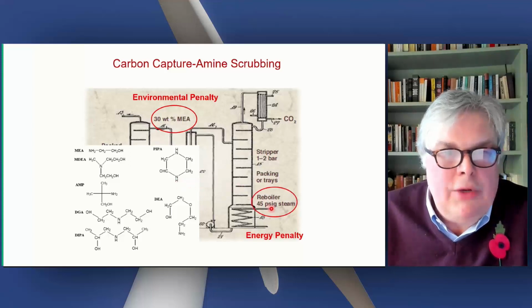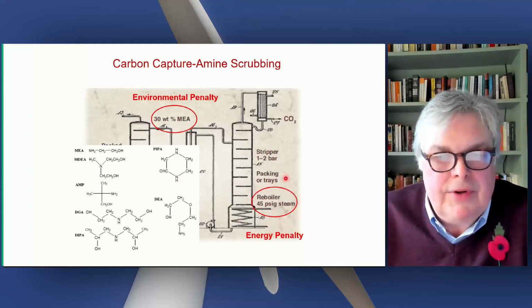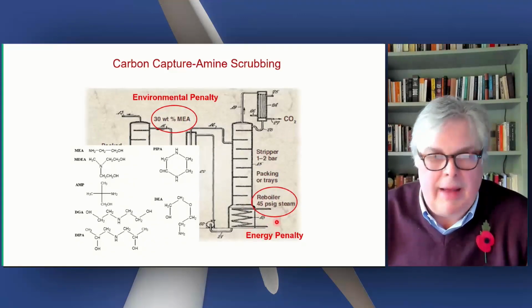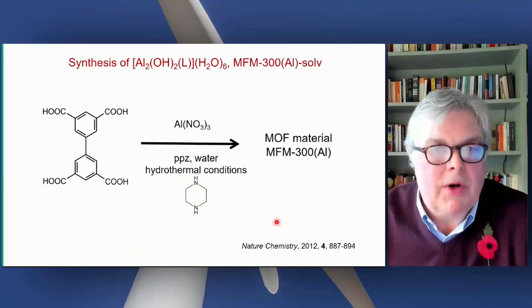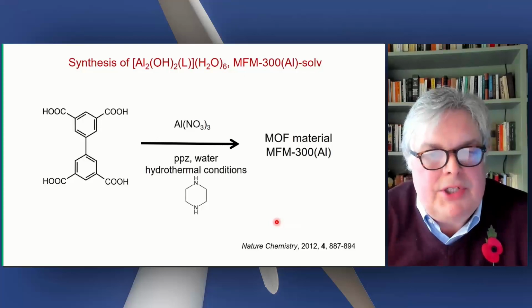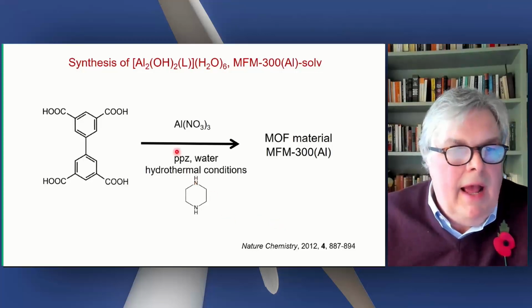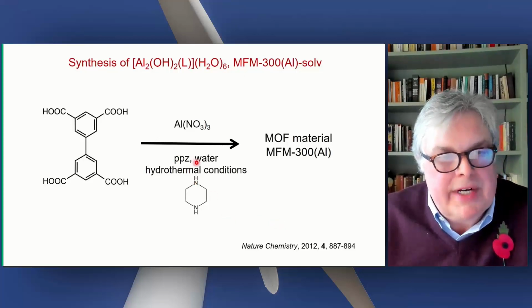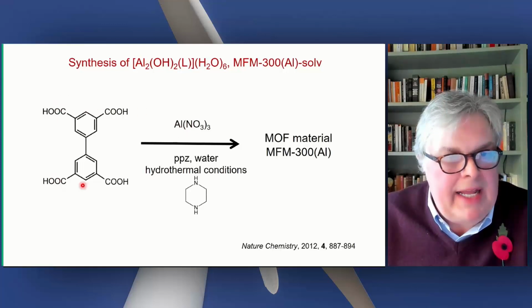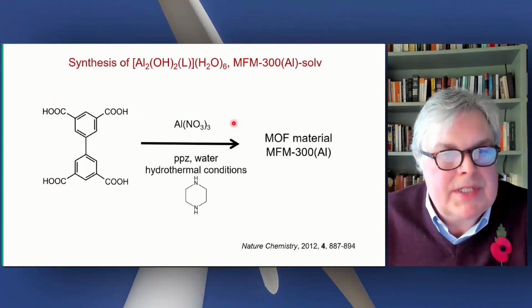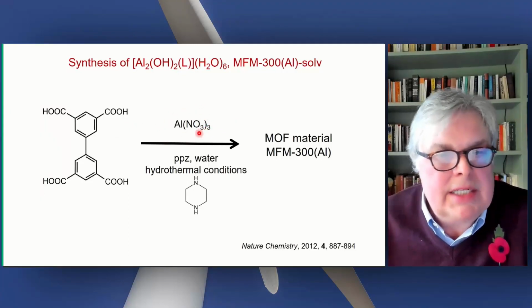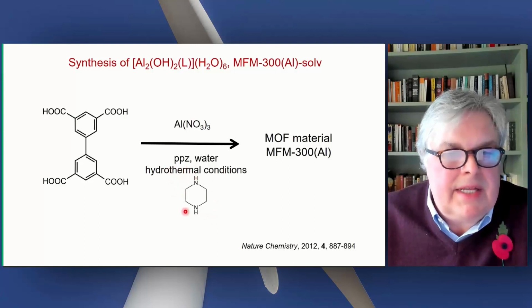And of course, in order to release the CO2, you have to basically heat the material up to release the CO2. So we were quite interested in looking at CO2 capture agents originally, but not using amine substrates. So this isophthalate, 4 carboxylate groups, react this with aluminium nitrate in the presence of PPZ, that's this. Under hydrothermal conditions, we can now make this material purely in water with an aluminium salt.